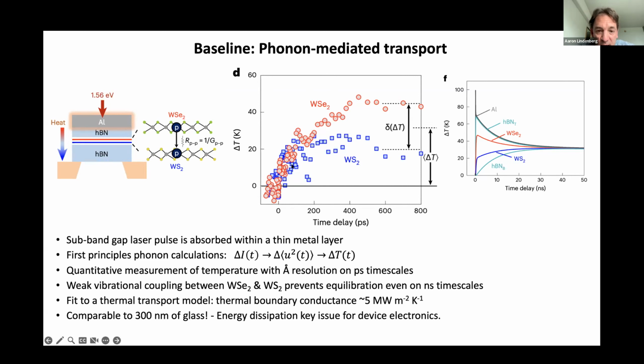So you can see that both layers start to increase right around time zero, right when the optical excitation pulse energy is initially absorbed into the top metallic layer. And then they increase on a few hundred picosecond timescales. And then at long timescales, even out to 800 picoseconds, you can see that the WSe2 layer in red and the WS2 in blue are actually still at different temperatures. So the thermal equilibration that is, of course, occurring has not yet completed.